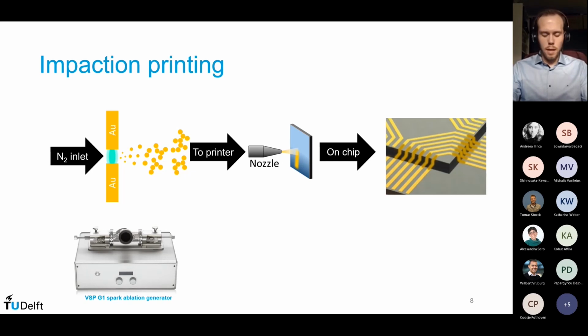Benefit of this is that we no longer need any chemistry. So our lines are very pure and clean. So there's also no need for any processing afterwards. The lines will work as is. It also means you have no storage of any materials. There's no ink storage or shelf life. There is no intermediate process. You make the particles and you deposit them immediately, which also makes the process quite a bit simpler. The last benefit is that you can use it on a lot of materials because there is no temperature, high force, or wet chemistry involved. So the only limitation is that it has to survive the jet itself.